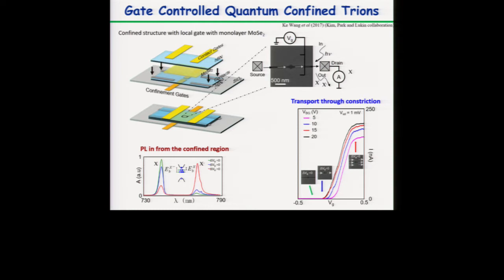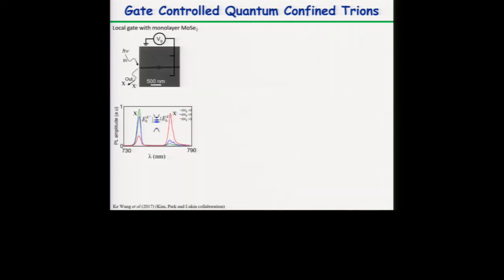So this is our local gates, so we can control the carrier density in parts of the MoSe2 while keeping these ungated regions that are only controlled by the bottom gate. So we can deplete or accumulate in these spots, right, in space, and we can see that this localized spot gets brighter or dimmer depending on where we gate the sample. So these are these confinement-induced features.